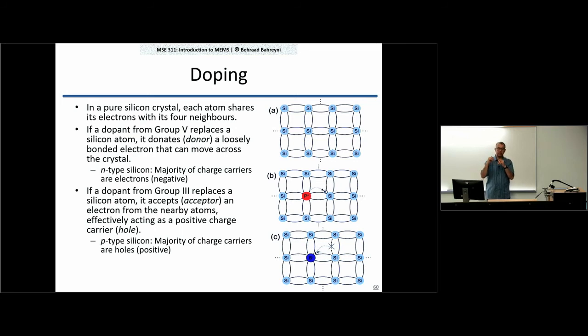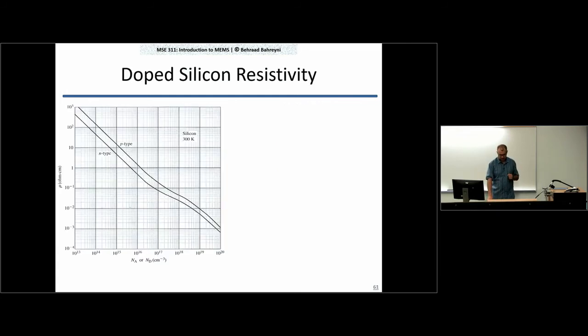Same thing with n-type dopants. If you increase the number of phosphorus atoms, you get more electrons. However, you can see that these two are working in opposite directions, right? An n-type dopant is donating an electron, a p-type dopant is accepting an electron. So if you add both of them, some will cancel each other. But when added on their own, each one of them is actually improving the electrical conductivity.